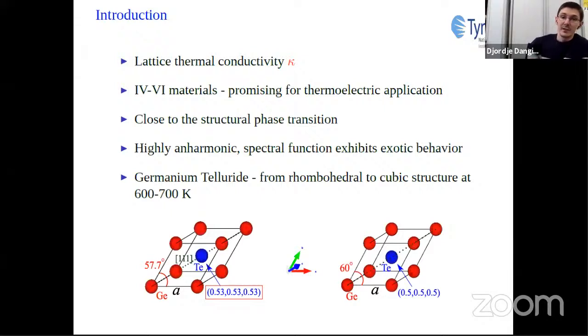This proximity to the structural phase transition makes these materials extremely anharmonic, which limits their phonon lifetimes. Additionally, this anharmonicity causes phonon spectral functions in these materials to exhibit exotic behavior. For example, in lead telluride, experimental results showed that the phonon spectral function exhibits double peak structures rather than the expected one peak structure. In this talk, I'm going to focus on germanium telluride, another example of the IV-VI materials and a promising thermoelectric material that undergoes a structural phase transition from rhombohedral to cubic phase at 600 to 700 Kelvin.